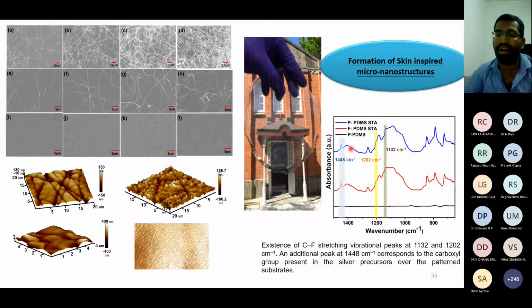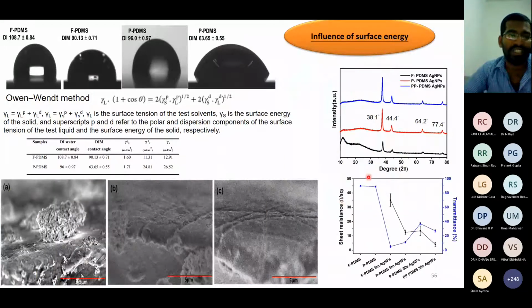So now we also try to characterize the silver nanoparticle formation by using FTIR characterization. And then we study the surface energy, because surface energy is quite important for good conductive substrate formation. So using the flat substrate, we are not able to get a very good surface energy. But if we tune these structures, we are able to get double the surface energy. So we can end up with very good crystalline silver nanowires, silver nanoparticles on P-PDMS.